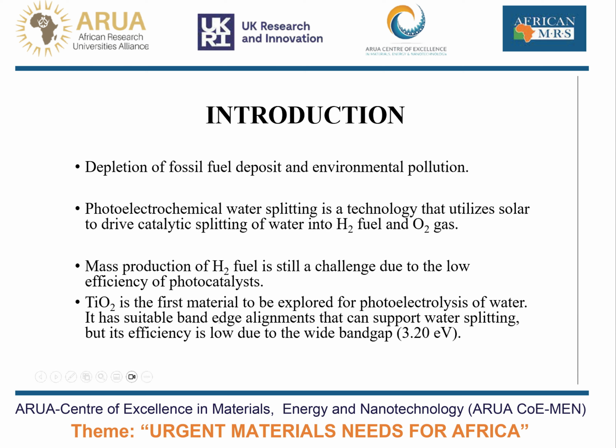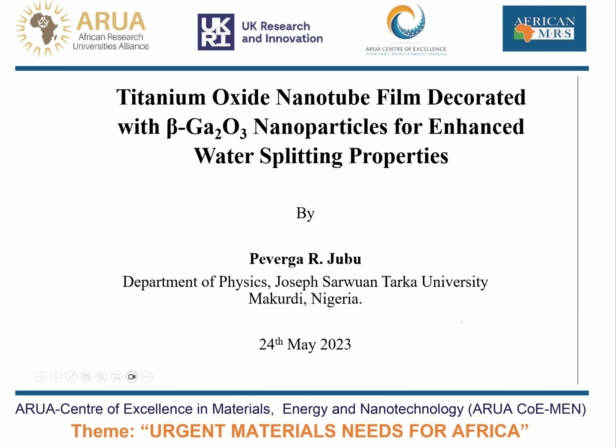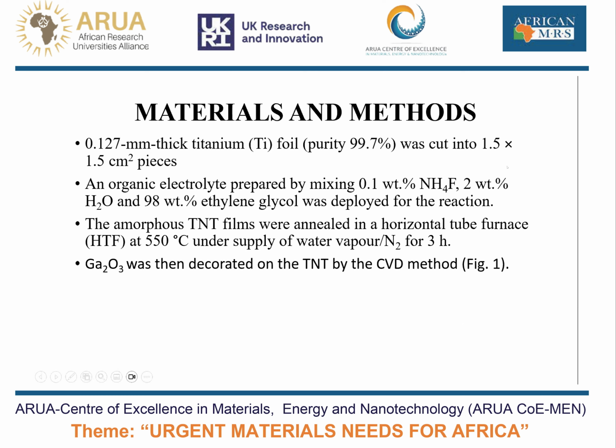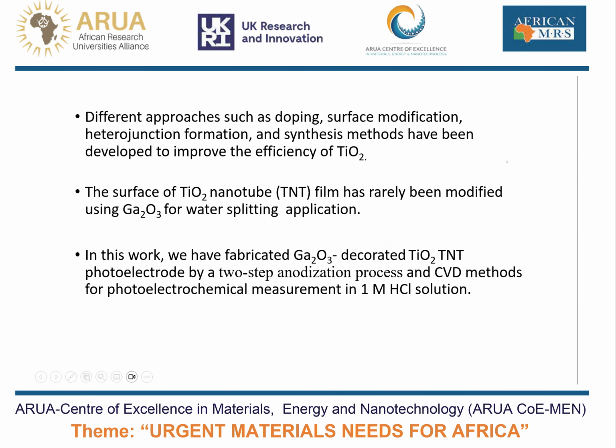Titanium oxide has a suitable band edge alignment that can support water splitting, but its efficiency is low due to its wide bandgap of 3.2 electron volts. Because of this, different methods are being exploited to improve the efficiency of titanium oxide for water splitting and for photocatalytic degradation of industrial waste.